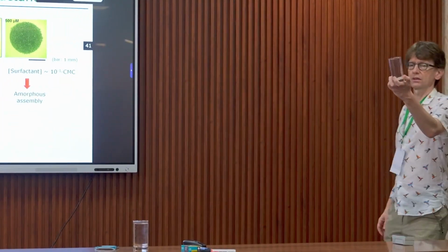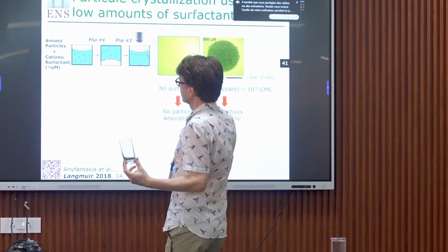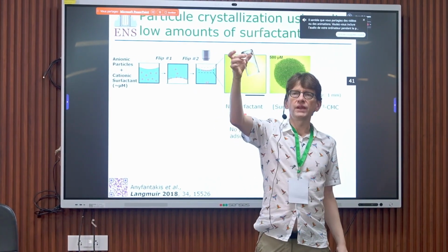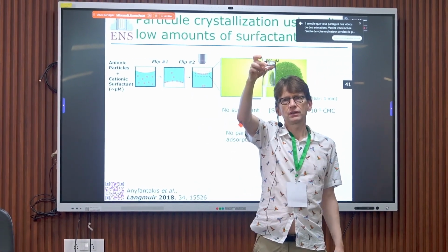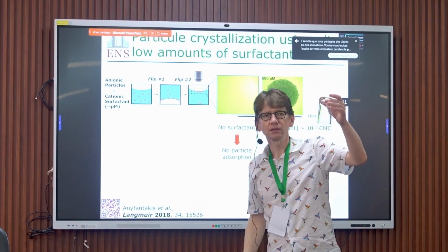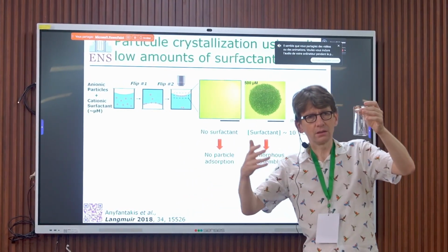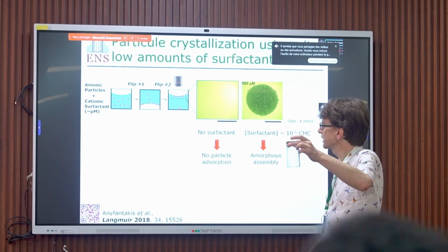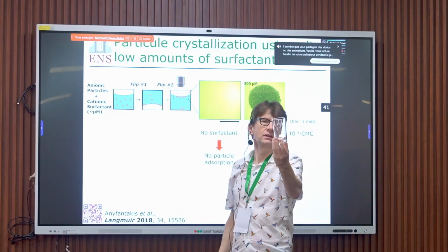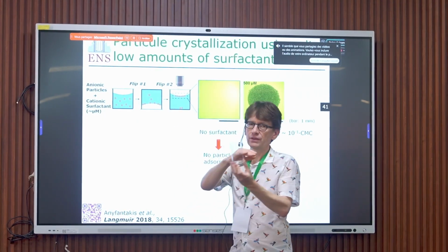So you take a smaller container, of course, because you need capillarity, and you put a particle suspension in the container and flip it. Your particles will finish by reaching the interface. You cannot work with 10 nanometer particles, but with micrometer or hundreds of micrometer particles, they will reach the interface. And then you flip again. This is the experiment. Very, very easy. And then you just look at the surface with a microscope.